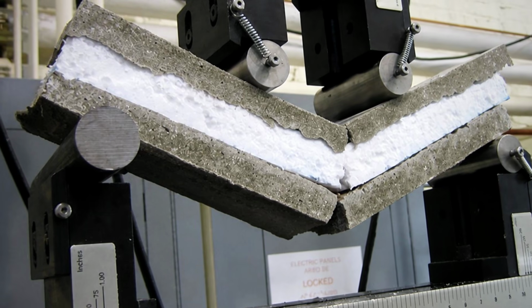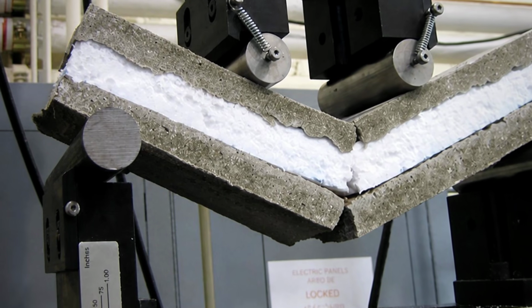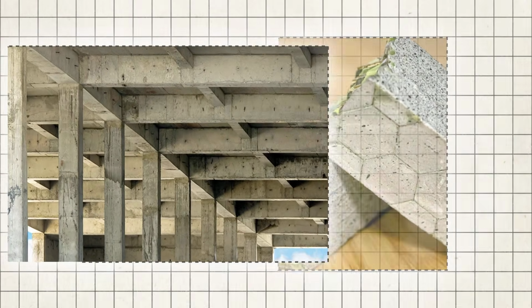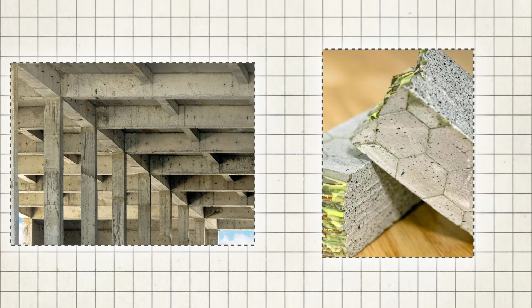And they did it without giving up the strength that makes cement worth using, which is the trap every attempt like this falls into. Usually you make concrete better at electricity by making it worse at being concrete, softer, weaker, useless for holding anything up. They avoided that trade. The material stayed strong and got conductive.